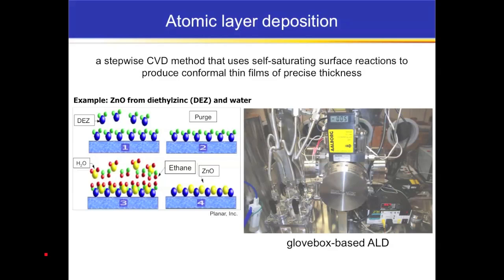You purge the gas out. And then you put in your water pulse. Water comes in and reacts again in a self-saturating monolayer fashion with the diethyl zinc adsorbed molecules there. You pump out the products, the side products. And what you're left with is basically a digital way to build up a zinc oxide film.